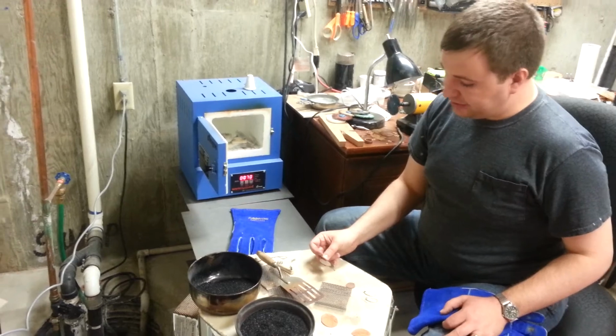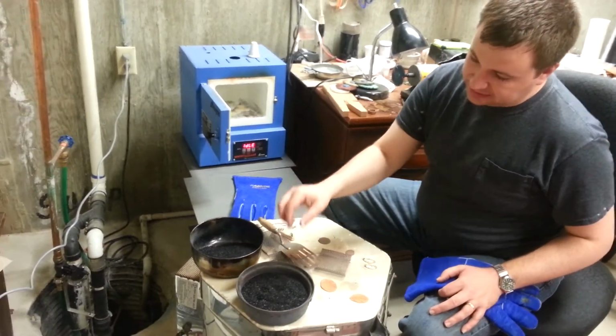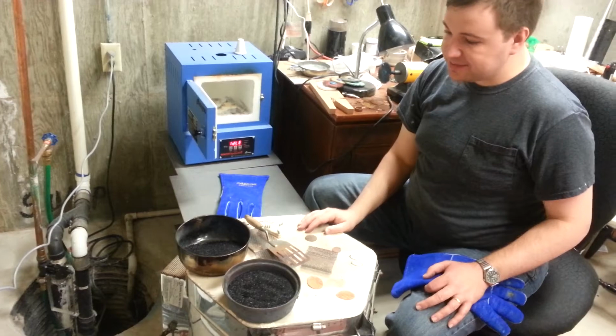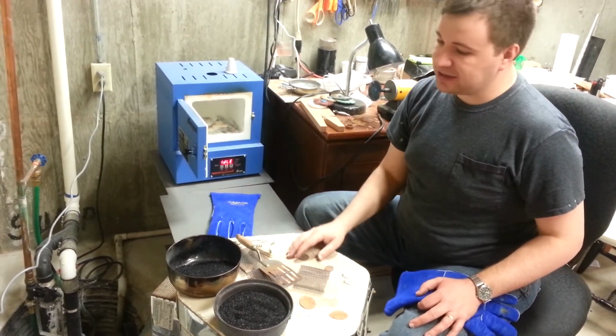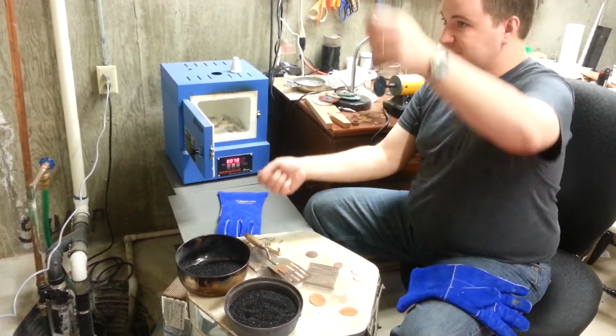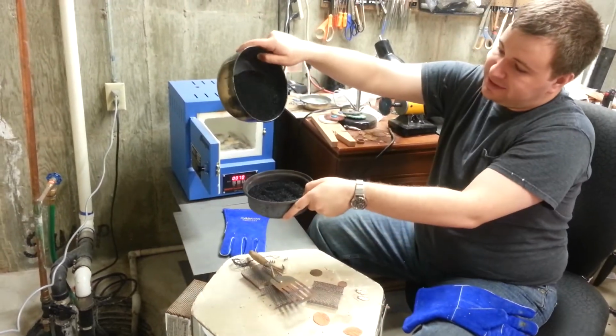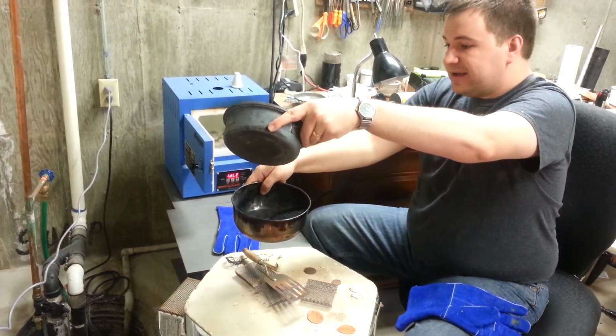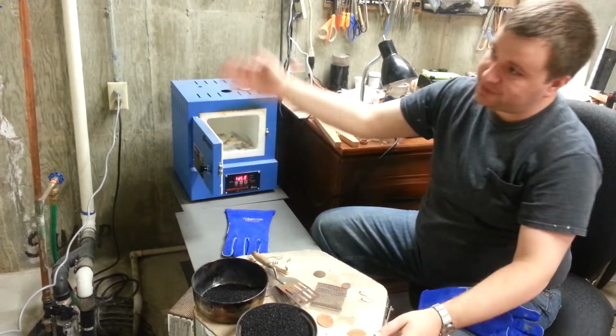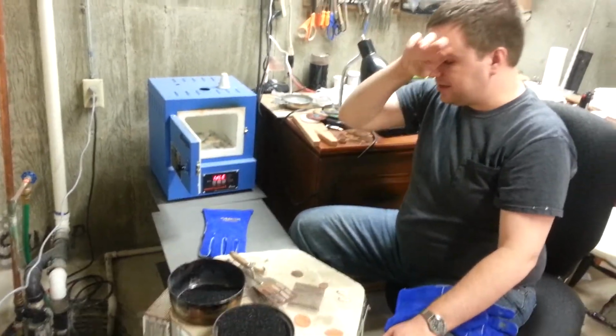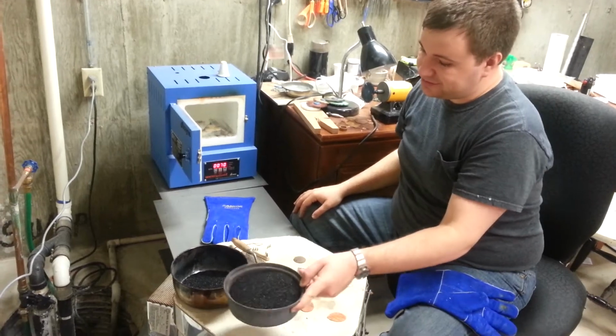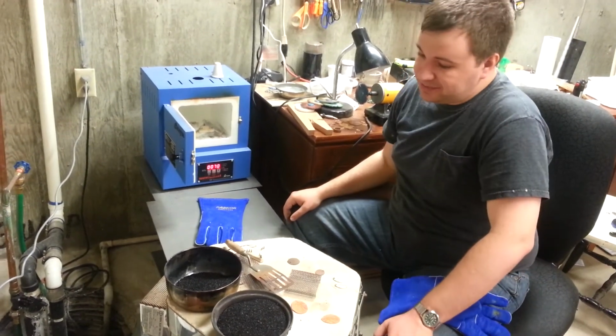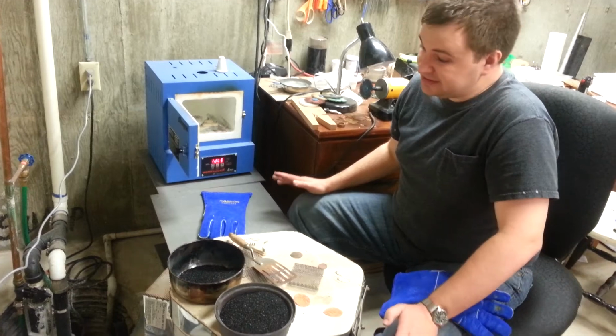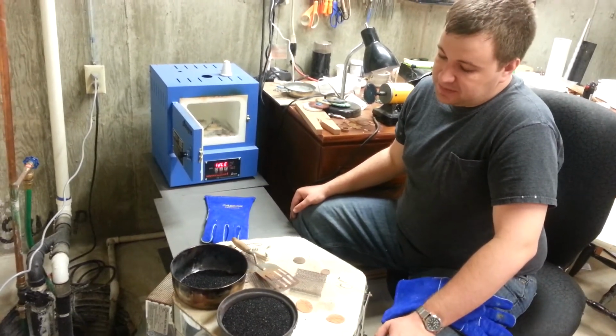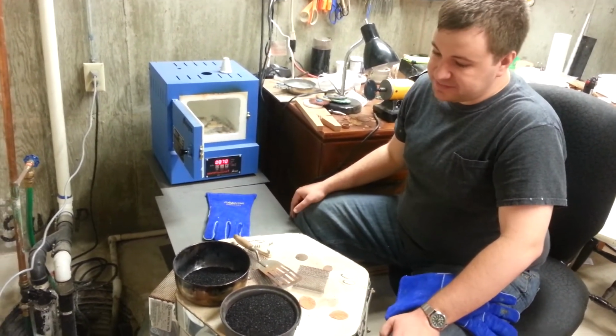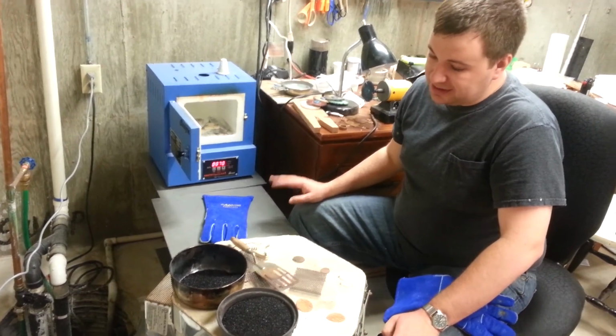So a note about the activated carbon: you can only use it 2 or 3 times, and then you've got to start a new batch. In between firings, you take 2 bowls and you kind of do this thing out in the wind outside, and you can get the wind to kind of blow away some of the ash. If you use it more than 2 or 3 times, it really doesn't absorb the oxygen as well, and you end up with pieces that just don't work. The carbon's not super expensive, and since you can use it several times, it's not too bad.